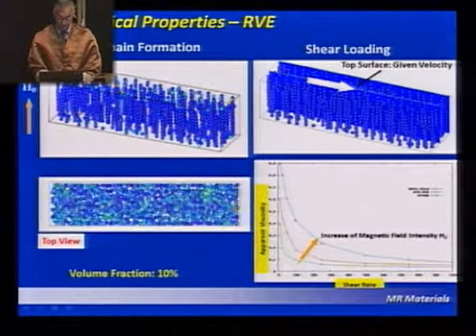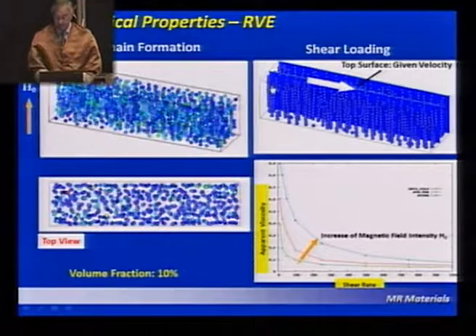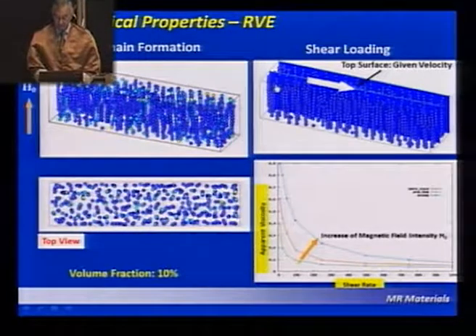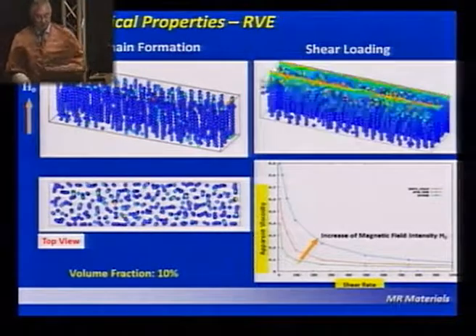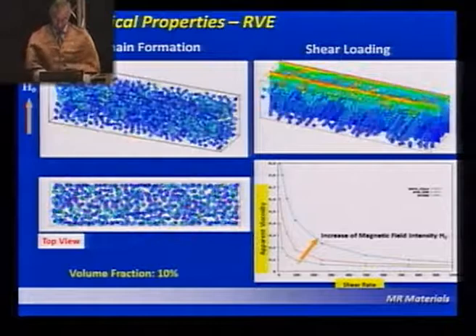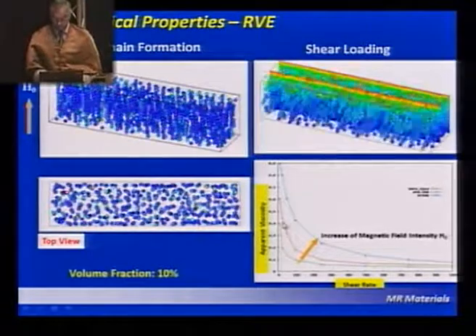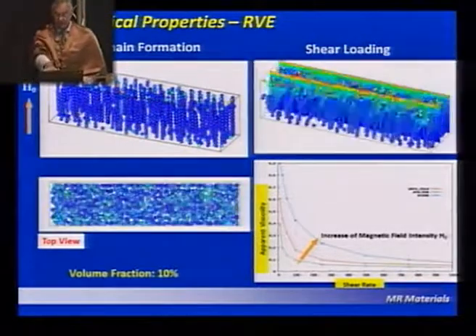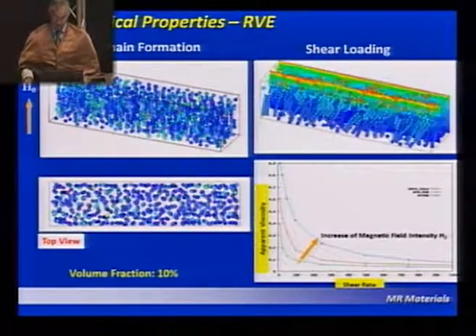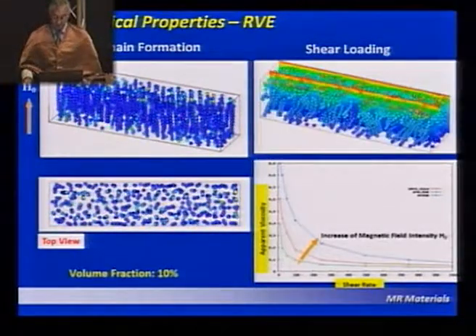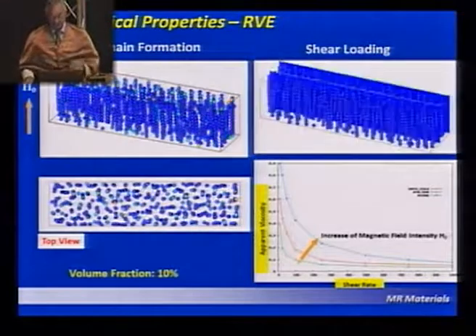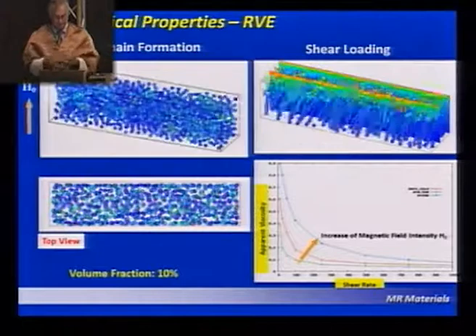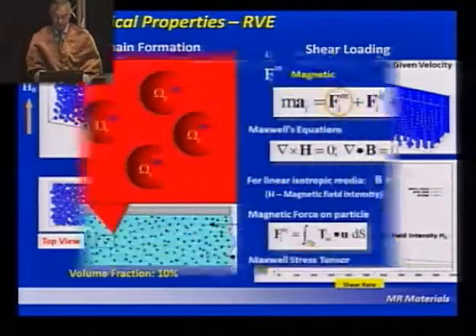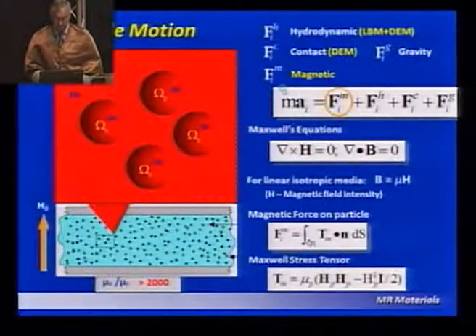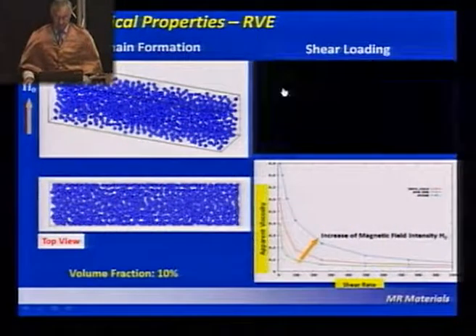So we form these chains, and then we apply a horizontal velocity to the top surface. Then we can compute the force on the top surface, and from the force we can compute the apparent viscosity. So what we have in the bottom picture is, as you change the shear rate, depending on the velocity you apply at the top, you find that as you increase the magnetic field intensity, you can actually increase the viscosity. And this change is instantaneous, so you can actually control the property of this magnetorheological material.